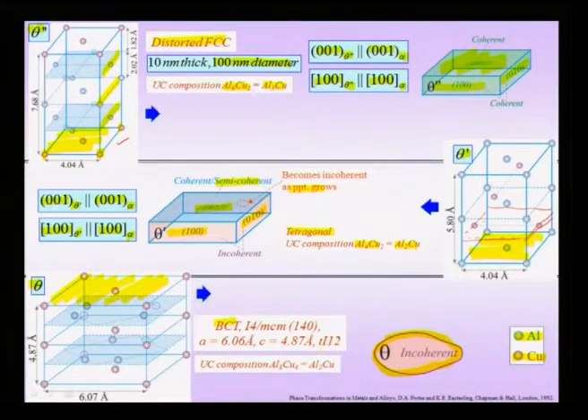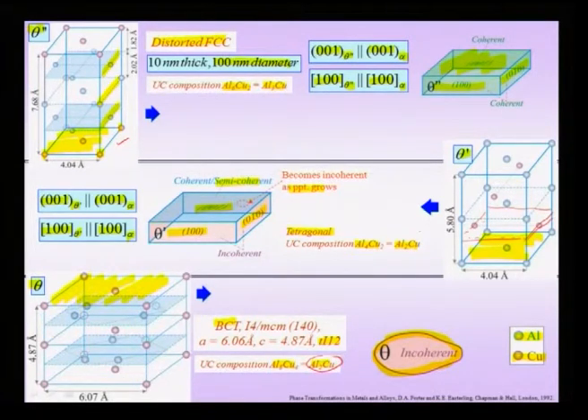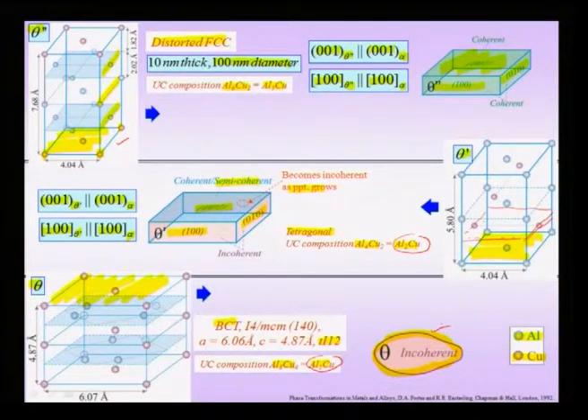This body-centered tetragonal structure has 12 atoms per unit cell with composition Al₈Cu₄ = Al₂Cu, identical to theta prime. That means as the precipitate goes from theta prime to theta there is no change in composition, and both are tetragonal phases. However, all interfaces are now incoherent, making them more glissile — they can grow faster — so theta precipitates tend to coarsen much faster than theta double prime or theta prime.